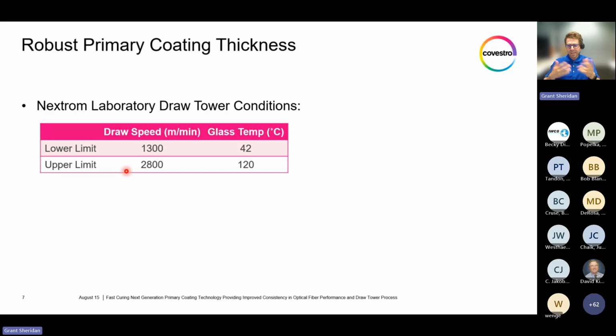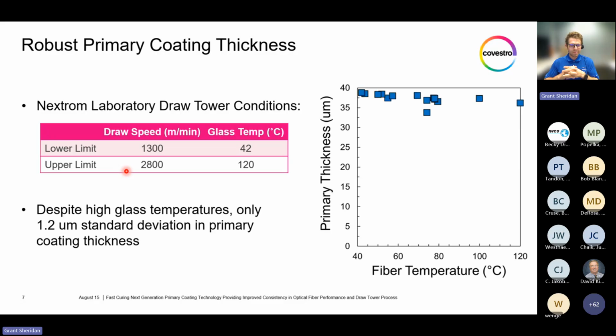Now, previous IWCS papers had noted that coating geometry, coating thickness, is a very large concern with fast draw speeds and high fiber temperatures, as controlling thickness over a range of process conditions would be very important for consistent fiber production. So one of the first properties we looked at was the primary coating thickness, shown here, over an 80-degree range of fiber temperature.